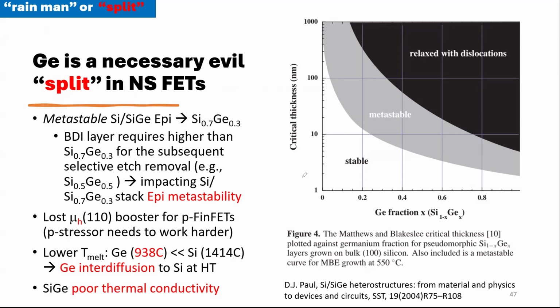On top of that, germanium problem. Germanium has much lower melting temperature. So if you have a problem when you grow the stack, it will diffuse to silicon. On top of that, okay, we talk about poor thermal conductivity. That's fine. I mean, you eventually can take it out. So that's probably okay. But here, that's a big problem.